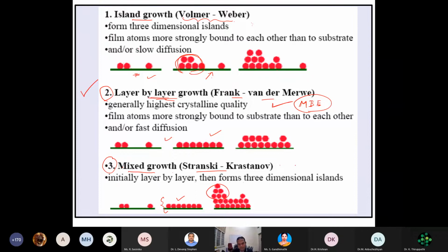So you have to remember that when I just take an MBE, layer by layer growth mode will not happen automatically. You have to fix the deposition conditions very precisely and monitor them very carefully so that this growth will take place. Otherwise, it will eventually end up in mixed growth mode or island growth mode until you monitor and precisely follow the particular deposition conditions. So that is very, very important.